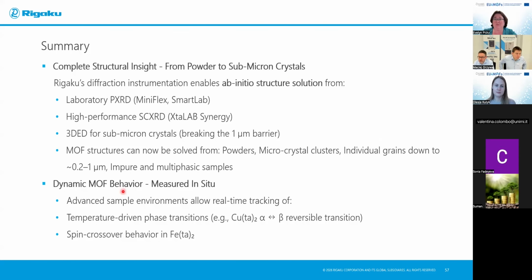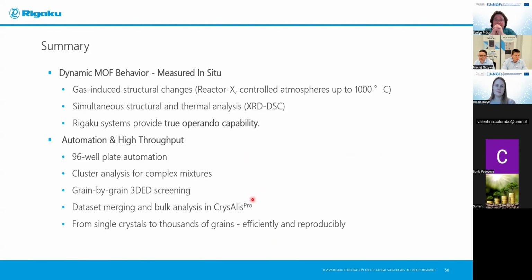So to conclude our presentation, Rigaku's diffraction instrumentation enables ab initio structure solution from powder data, from single crystal data, as well as from electron diffraction. We can solve the data from samples like powders, microcrystal clusters, individual grains. We can investigate dynamic MOF behavior, performing measurements in situ, non-ambient. Also, we can perform studies like gas-induced structural changes. We can observe simultaneous structural and thermal analysis. And as well, we can also offer full automation and high throughput for MOF synthesis.